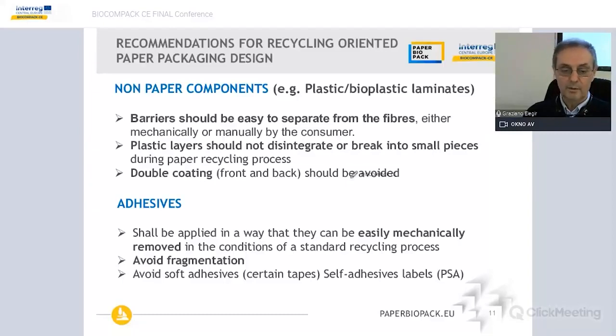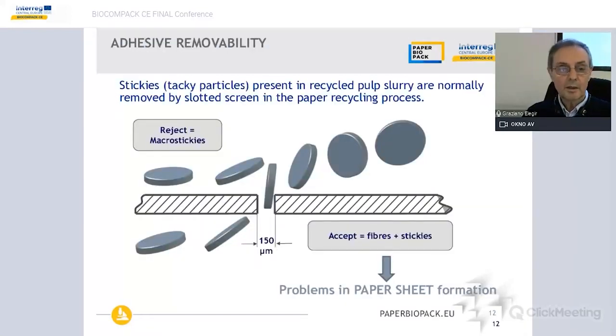And one general recommendation is that we have to avoid the soft adhesive, and particularly self-adhesive labels, the pressure-sensitive adhesive, that are definitely detrimental in the process, because they are very small, very tacky, and they really cause a lot of trouble during the recycling process. Concerning adhesive removability, in this slide, probably you can understand better why they should not break into small pieces.